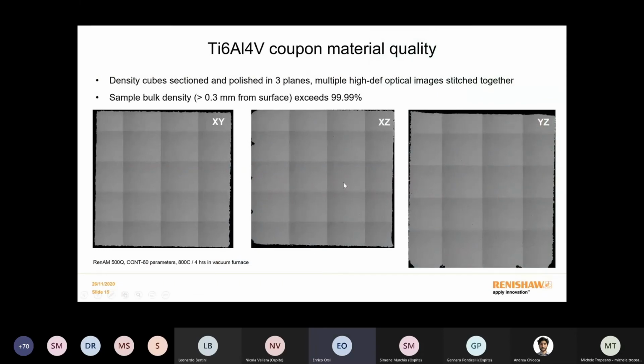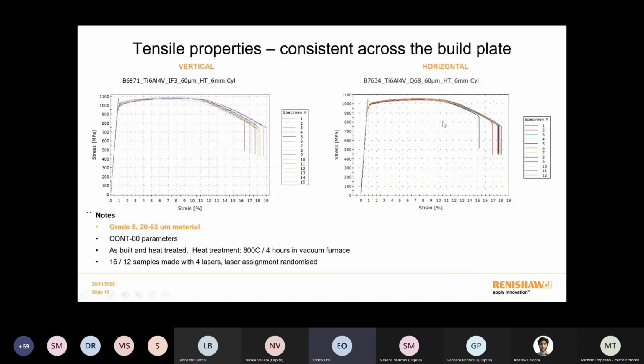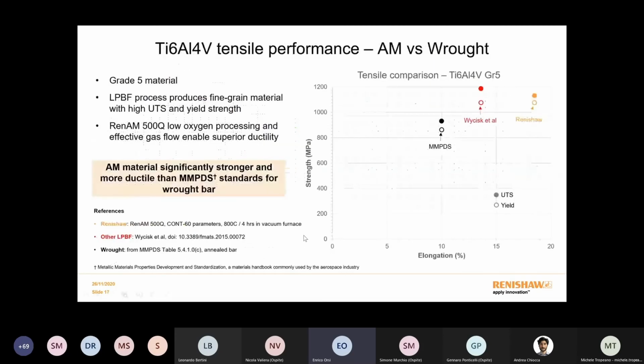If you look at a good part that is coming out of this process, these are micrographs. You can find densities that exceed 99.99%. Sometimes you have very small porosity, like in this area. However, the bulk of the part is very dense. So this is the first step when you develop a material: to achieve very good density. A second step is to achieve good tensile properties, consistent all over the powder bed and consistent in time and over different processes.